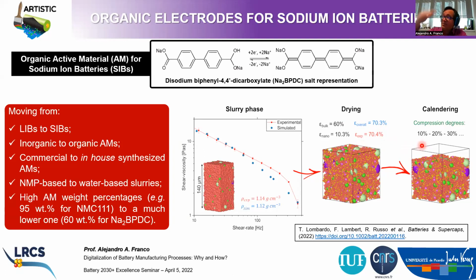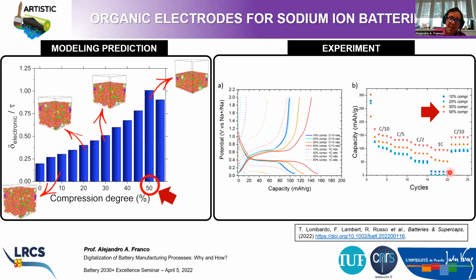And then we perform calendering of this virtually generated electrode microstructure. We compress at different degrees: 10% means you compress 10% of the initial thickness, 20% of the initial thickness, and so on and so forth. And then we characterize these virtual electrode microstructures in terms of their electronic conductivity and in terms of their tortuosity factor through the pore network, which is supposed to be wet with the liquid electrolyte to transport sodium ions. And then we plot this kind of graph here where you see the ratio between the calculated electronic conductivity divided by the tortuosity factor of these virtual electrodes.